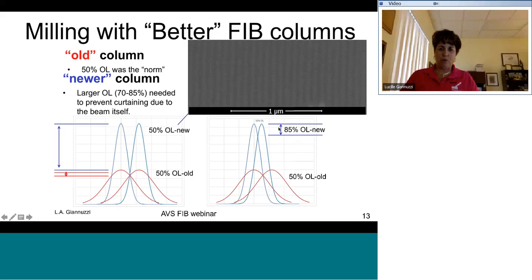So the problem, not necessarily a problem, but you have to be aware, is that when you change this to 85% overlap, you're using more patterning overhead, in the sense that now I need more pixels here, or the beam has to hit more spots from here to here, versus, for example, an older beam where the beam itself is larger. Okay, does that sort of make sense? But anyway, you just have to be aware of that. So for some of the newer columns, the vendors specify that you need to go to a larger overlap to prevent curtaining due to the beam itself. So it's just something that you should be aware of.